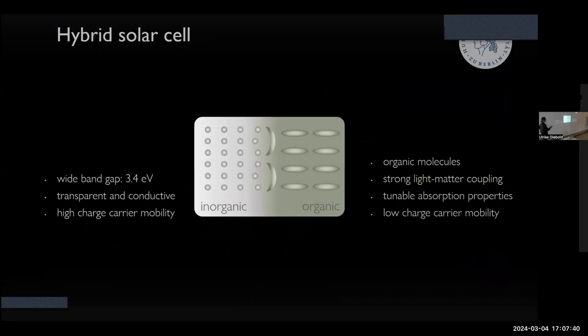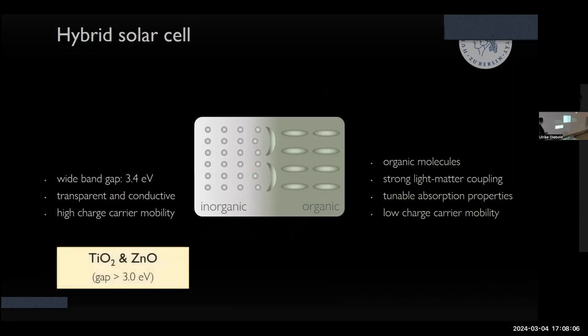The reason is that the inorganic ones are often transparent and conductive and can have high charge carrier mobilities, which are useful for technological application. While on the organic side we have chemical tuneability and a very strong light matter coupling that we have under control, or at least the synthesis tell us they have it under control. Candidates for inorganic semiconductors are commonly used TiO2 and also zinc oxide. They have a band gap in the near UV, so visible light can just go through it,